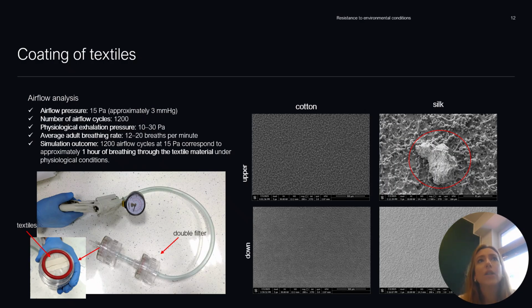To answer the second question regarding the potential use of these materials, for example, as a protective face mask, we simulated breathing conditions using an artificial airflow model. The textiles were exposed to an airflow pressure of around 15 pascals, and the cycles were 1200. It corresponds to around 1 hour of physiological breathing. This enables us to assess the stability of the nanocomposite coating and the fabrics under realistic conditions.